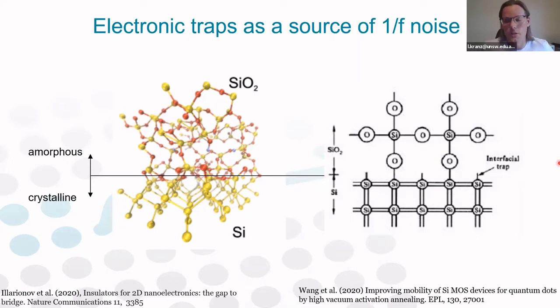Well, let's look, for example, at the interface between silicon and silicon oxide. So what we have here is basically a phase transition between crystalline phase and amorphous phase. And in principle, the defects can be found anywhere in this picture. However, in electronic devices, the wafers are already grown as a single crystal, so with really low defect density. So you would expect relatively low defect density in the crystal itself, and the literature points out that the defects are more likely to be found on those interfaces between different materials or in the oxides themselves.